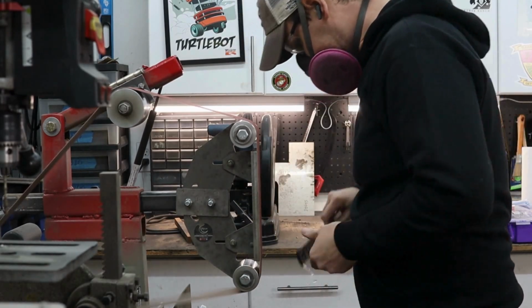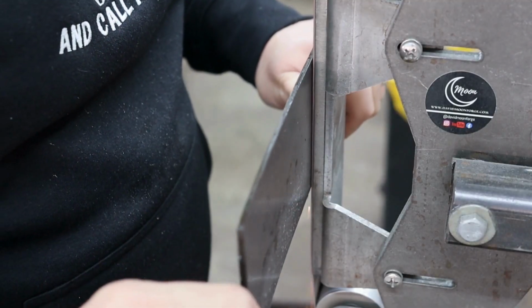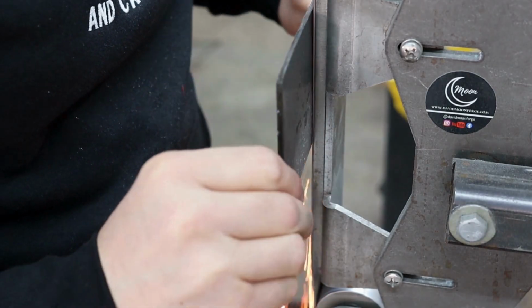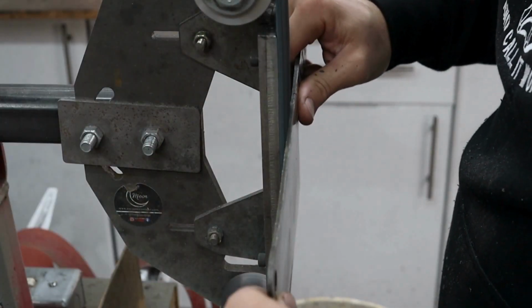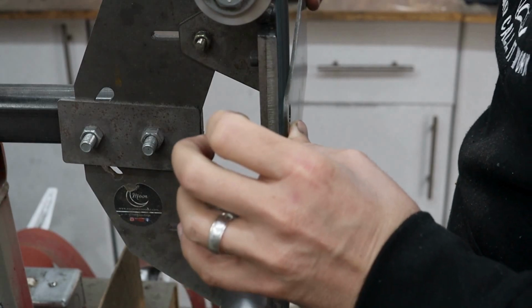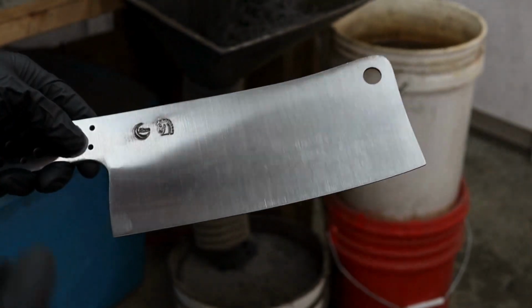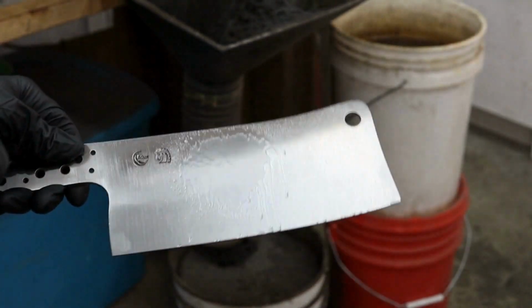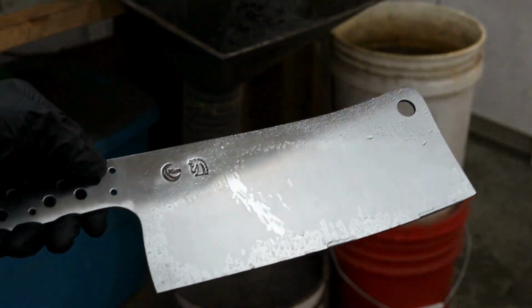I'm going to take this up to a 220 grit finish on the 2x72 and then polish it up a bit with a very fine surface conditioning belt loaded with black rouge. This is just so I can do a test etch and make sure that the core steel is well centered and that I haven't ground through any of my outer layers of Damascus.